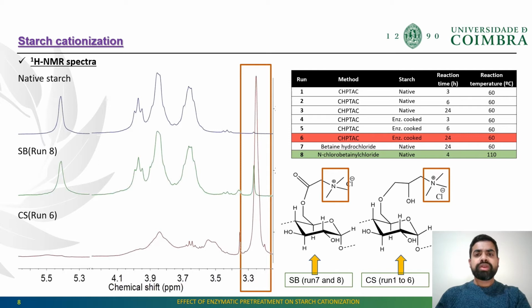In addition to calculating the DS, proton NMR spectra can also be used for investigating the detailed structure of modified starch. The peak at 3.5 to 4 represents the hydrogen attached to the different carbons of the anhydroglucose unit. A singlet at 3.2 ppm, due to the hydrogen of the methyl group attached to the quaternary ammonium group in cationic starch, confirms the presence of the cationic group attached to the anhydroglucose unit. The DS was also calculated using these NMR spectra for each reaction.